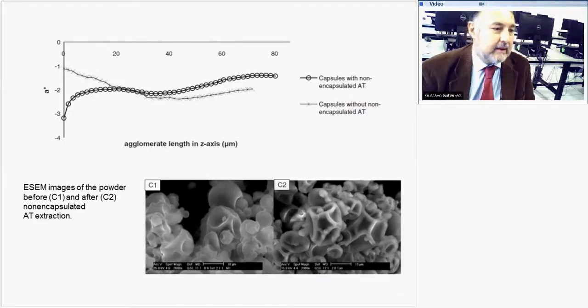And the color parameter a, of course, with non-encapsulated alpha tocopherol was lower than the capsules with encapsulated alpha tocopherol. And the impression that we have by means of scanning electron microscope of both capsules, before and after the extraction, is that the structure shows more spaces here.